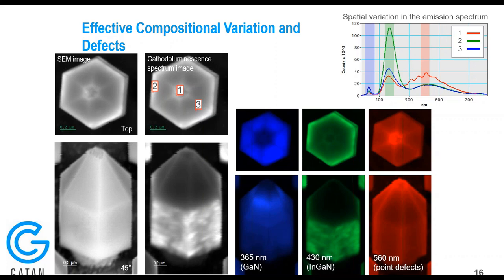If you recall, the gallium nitride peak was most intense around the center of the blue. So here, it was the most intense. Here you have sort of the opposite effect, where it's intense towards the outside as opposed to the peak. You can see the indium gallium nitride is a little bit brighter towards the center, indicating some sort of enhancement that's coming from the array. And likewise, the point defects are modified in a way that they're bright towards the center as opposed to the outside. What you can also see is that in the spectrum coming from point 3, up in the top right of the screen, you can see several peaks in the defect band that were not there before. And so that's another enhancement effect that's coming from the array.